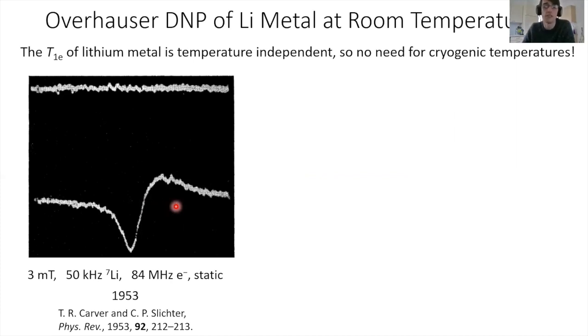But these are very different experiments to what we now consider as contemporary DNP. They're at very low fields. This is 3 millitesla, so your lithium is at 50 kilohertz, electrons are 84 megahertz. They're under static conditions. And importantly, they're also performed at room temperature. So typically DNP is performed at 100 Kelvin or even lower. That's to slow down the electron relaxation so we can harness its polarization. In the case of lithium metal, the relaxation is temperature independent. So there's actually no benefit to cooling down. And this works just as well at room temperature.